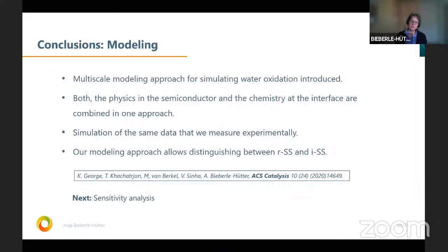So the conclusion from the modeling is that we use a multiscale modeling approach for simulating water oxidation. And we have included both the physics in the semiconductor and the chemistry at the interface. So it's a combined approach here. We simulate the same data that we experimentally measure. And we are, for example, able to really distinguish between the RSS and the ISS. What we have at the moment started is a sensitivity analysis. I mentioned shortly, we have a long list of parameters. We now need to figure out which are the most important parameters to affect our data. And there we have hired a person from control theory who knows how to deal with a lot of parameters and do a sensitivity analysis. And we use this now for microkinetic modeling analysis. And I'm very curious what comes out here.